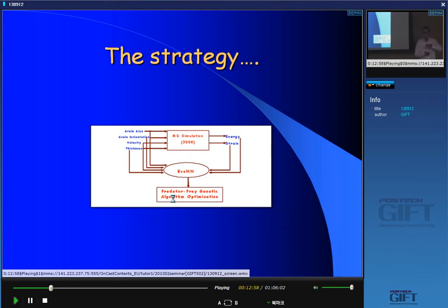create on the computer an artificial assembly of iron coated with zinc with all the phases that I talked about. Creating those phases is not so difficult because there is enough information about their crystal structure, and about many of the other required properties. So actually we can simulate that layer of coating that we have talked about. Now, classical molecular dynamics, that's what we are doing here, allows us to shear that assembly and then see exactly how it moves, how it fails, and what happens to it after a while.